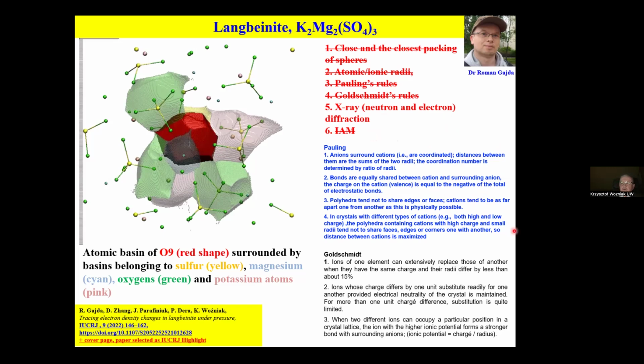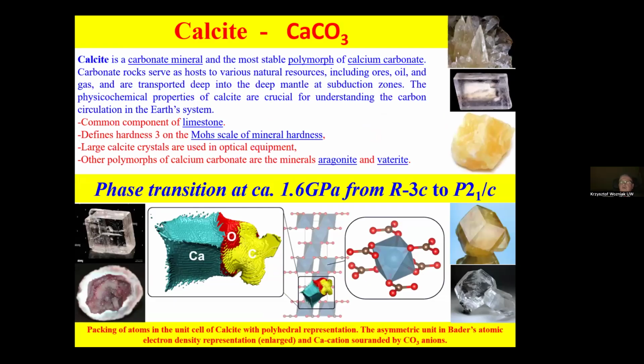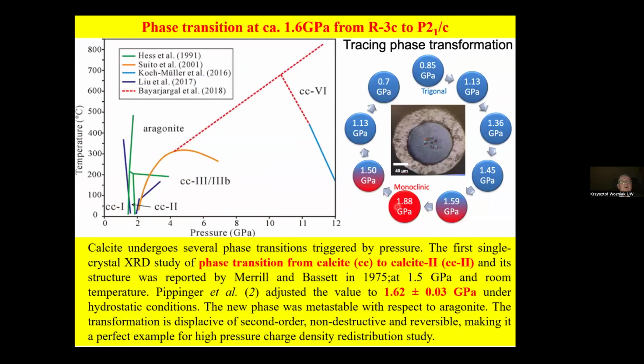But we are getting new tools which are very sensitive to interatomic interactions. Now, the second example, calcite. Calcite is a very common mineral, the most stable polymorph of calcium carbonate. Here you see the structure and the independent part of the unit cell in this atomic basin representation. It undergoes quite a few phase transitions, but we have focused our attention on the very first one, from calcite 1 to calcite 2, which is taking place at 1.62 gigapascals.